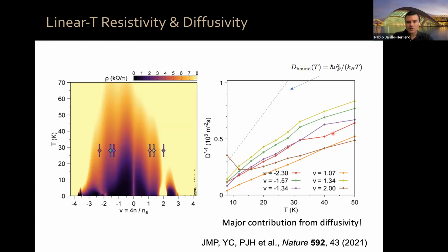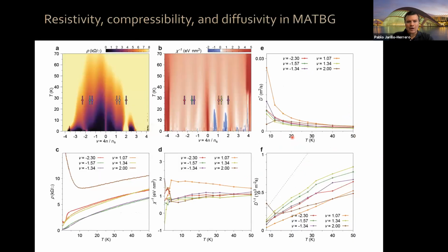Just to give you an idea, there is also a bound on the diffusivity given by fundamental constants and also VF and T, which is up here, and we are below that bound. So you have here all three data together for you to look at. These are the first measurements of the electronic diffusivity in a solid state system by combining resistivity and compressibility measurements, and this is what we recently reported.